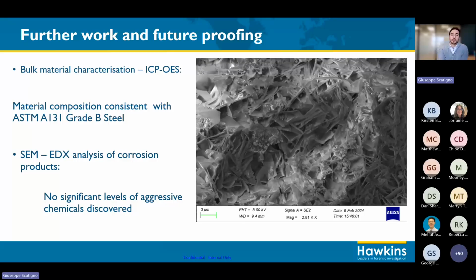This is inductively coupled plasma. We can effectively tell exactly what composition of metal we're looking at, and we're able to compare that with the standard. And by doing SEM, scanning electron microscopy, and energy dispersive X-ray of the corrosion oxide, we can then tell whether or not this has been contaminated, for example, by really acidic or really caustic solutions that may have expedited the corrosion. Therefore, we were able to prove that this did not happen, and therefore that all of the corrosion that we see was due simply to the lack of appropriate protection.